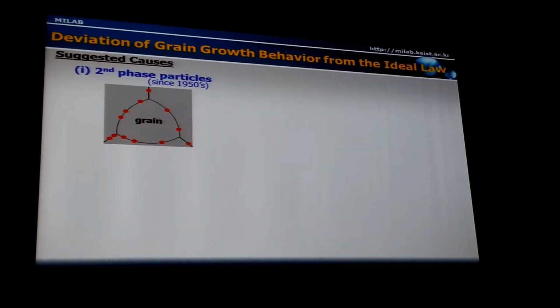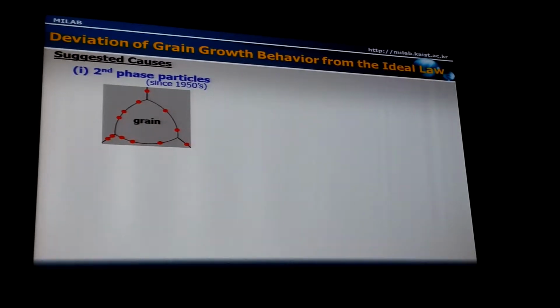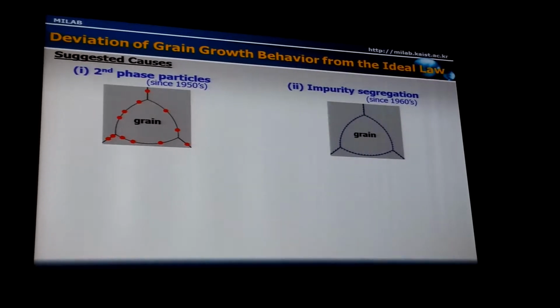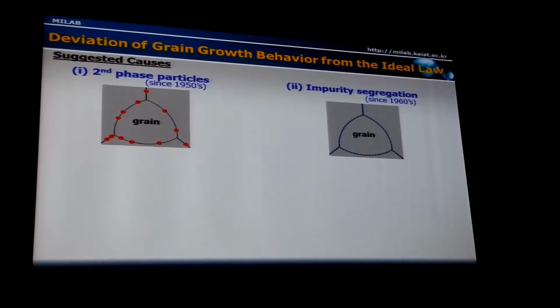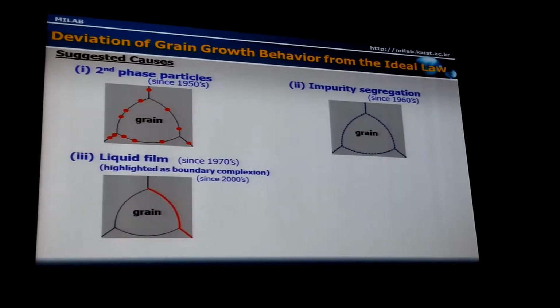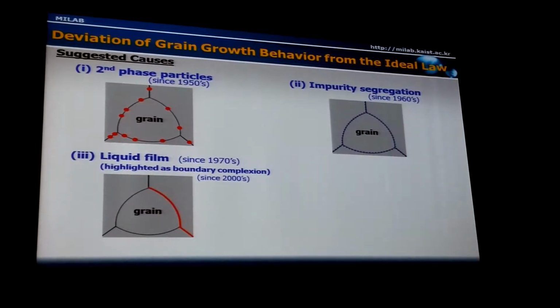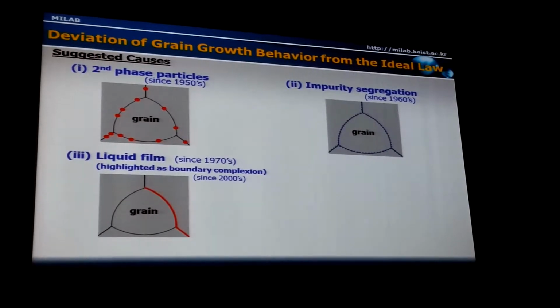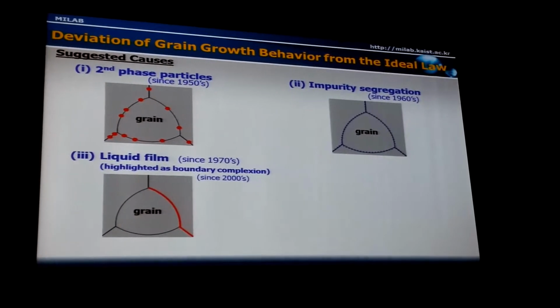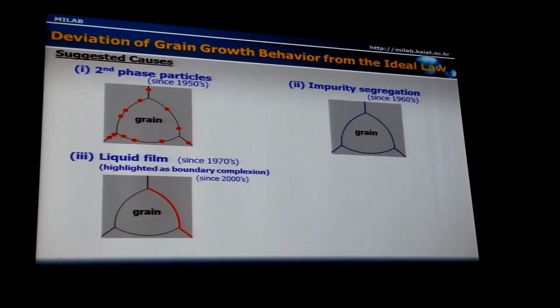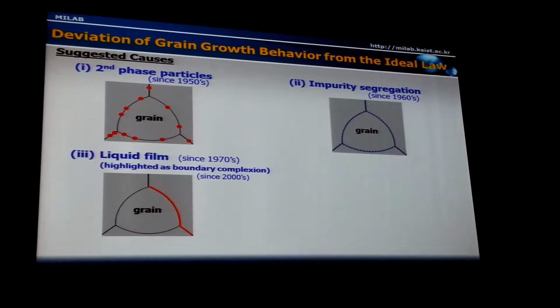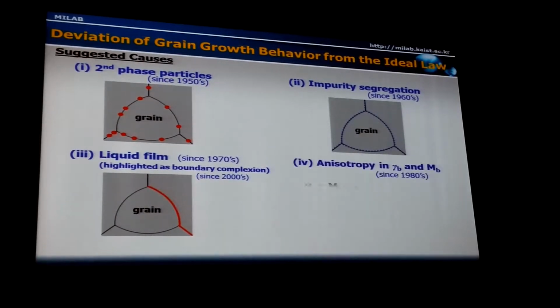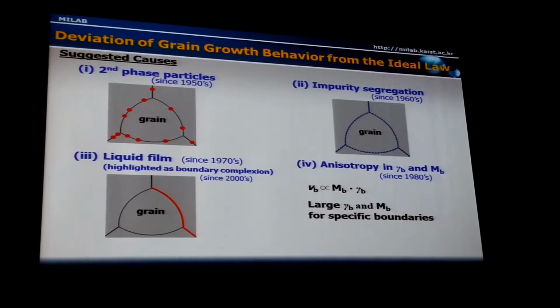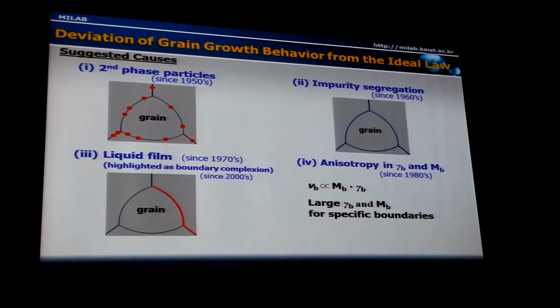For abnormal grain growth, several causes have been proposed. One cause was the presence of second phase particles at the boundary. Another cause, suggested in the 1960s, was the segregation of impurities at the boundaries. Another cause is the presence of a thin liquid film in certain grain boundaries. It was suggested in the 1970s, but recently revived as the different types of boundary complexions by Martin Harmer and his co-authors. And another suggested cause was the anisotropy in grain boundary energy and mobility.